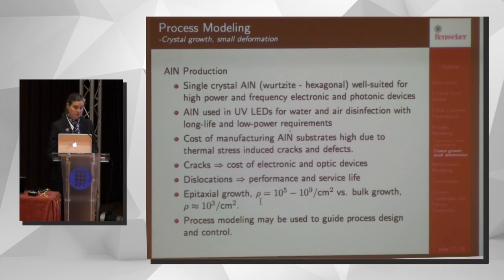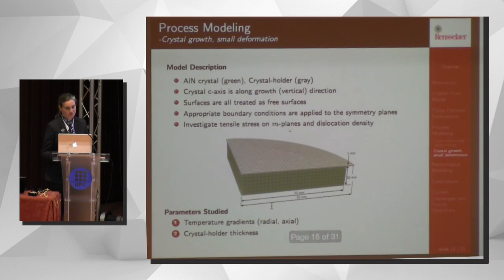Problem is, when you have this very low dislocation density, the material is pretty brittle, and they have a real problem in their process with the material cracking, and they have very high residual stresses. It's done at a very high temperature, and so they're interested in understanding this process, to model the process, to understand what are the key factors causing that cracking, and at the same time, they don't want to introduce dislocations, so we wanted to develop models to guide the process design.